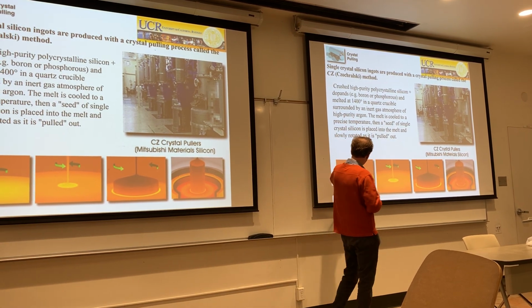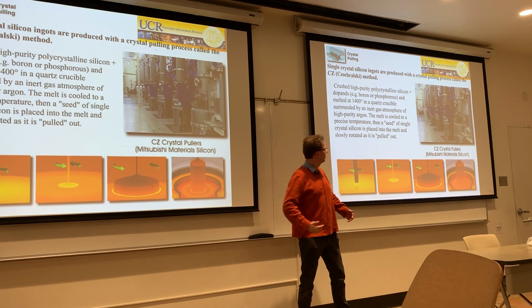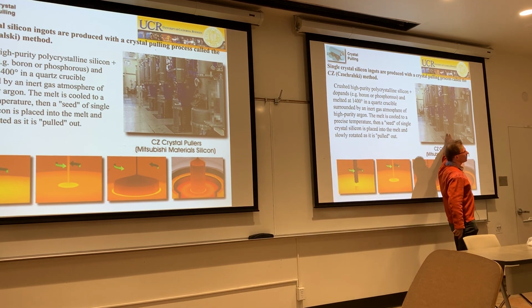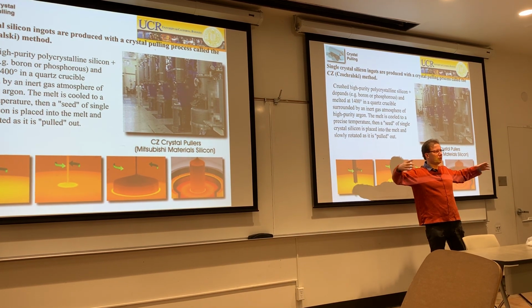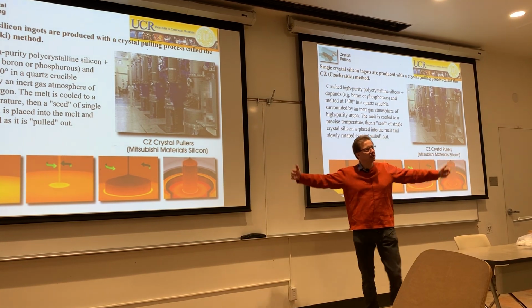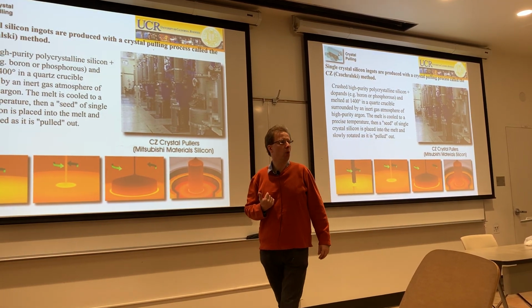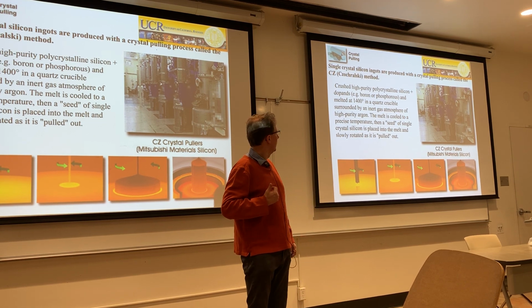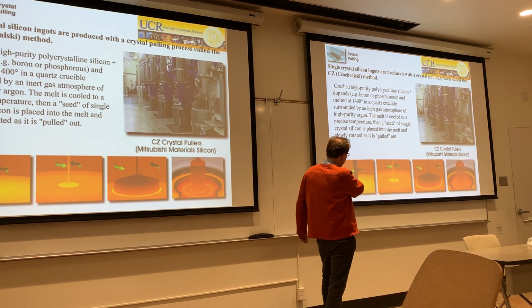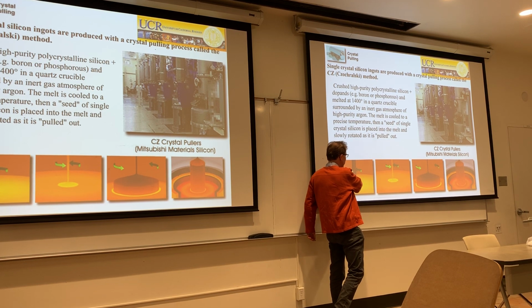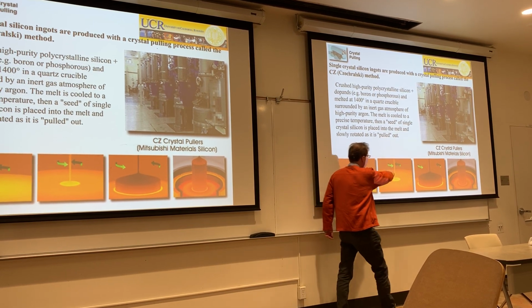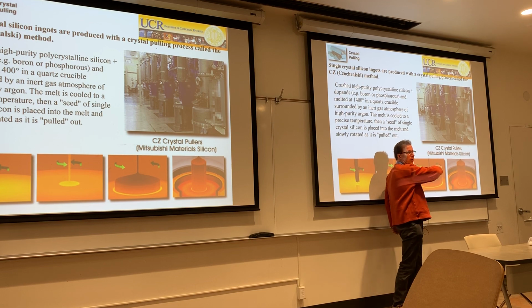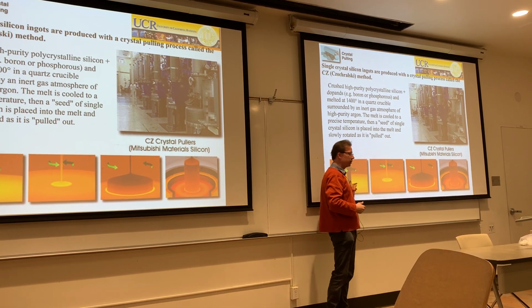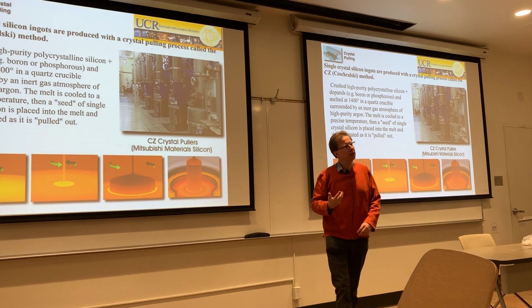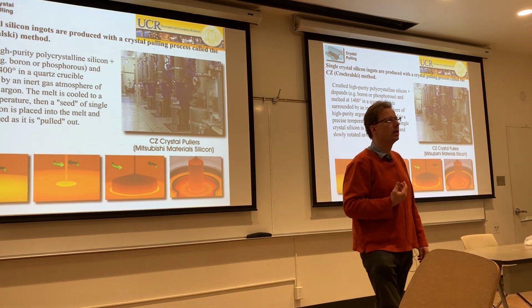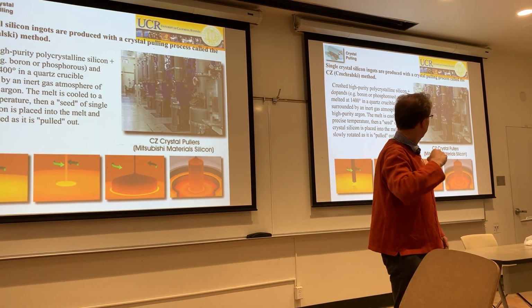So you start out by having a big molten vat, looks like this, except those were old style machines where the ingot was this big, now the ingot is this big. So the machines are bigger, of molten silicon. And you dip a very small piece of the silicon crystal into it, spin it, and then pull it slowly up, with some cooling along the way, very slow cooling. And it takes maybe 3-4 days to pull it slowly up, and you get an ingot.